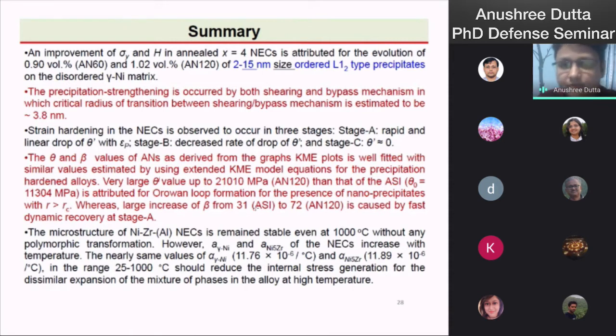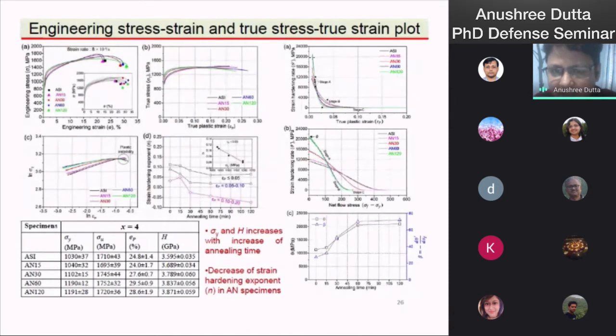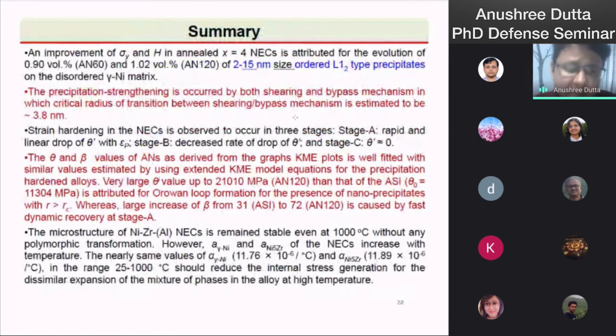The strain hardening of the NEC is observed to occur in three stages: stage 1 is a rapid and linear drop of theta, the strain hardening rate. The theta and beta values, strain hardening and dynamic recovery, of the annealed sample are derived from the Kocks-Mecking plots and are similar to the values estimated using the extended KME model equation for the precipitation hardened alloy. A very large strain hardening rate is obtained for the annealed specimens as compared to the as-cast specimens, attributed to the formation of Orowan loops around the nano precipitates of radius greater than the critical radius RC. Whereas the large increase of dynamic recovery from 31 to 72 is caused by fast dynamic recovery at stage 1.